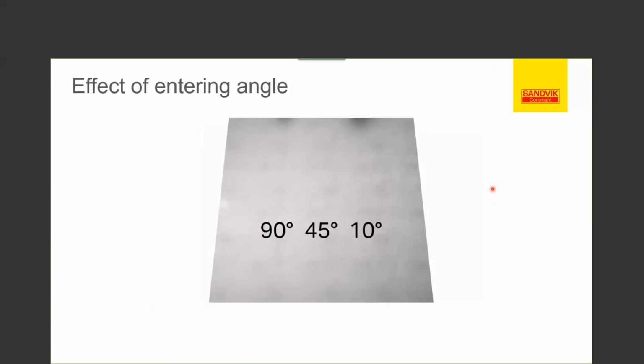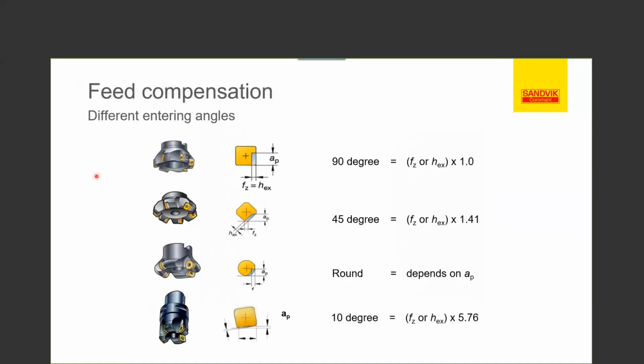So if you take a 90-degree, a 45-degree, and a high feed cutter and run them side by side, essentially what happens is we're going to get a chip thinning effect. So we need to increase our feed in order to maintain the proper chip thickness. If you take a 90-degree cutter, for instance, your chip thickness and your feed are identical. You have a factor of 1. And as we stated earlier, when it comes to a 45-degree, we actually have a 40% increase in productivity. So we need to increase that by 40%, or multiply our chip thickness by 1.4, which would be our feed per tooth.